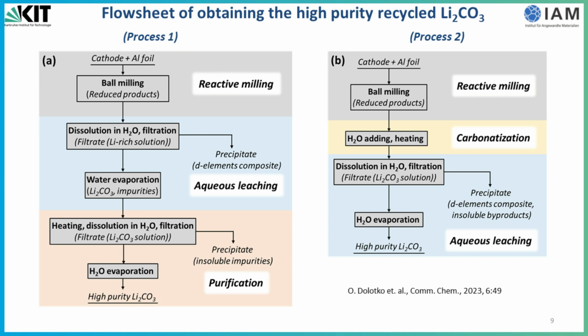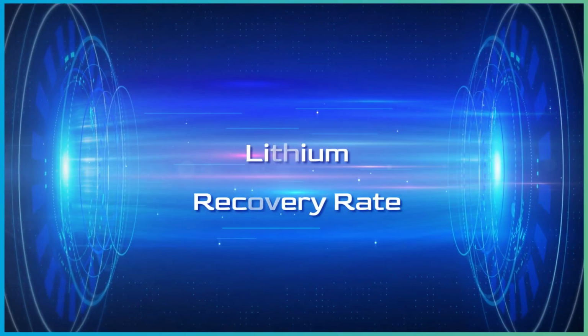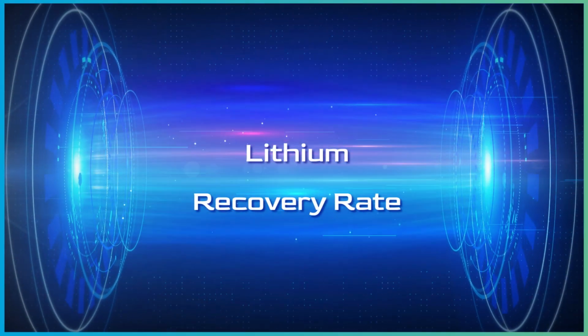In order to reduce the number of steps, we also developed a second process, where after reactive milling, we introduce a so-called carbonatization step. After this step, after washing, leaching with water and filtration, we obtain again high purity lithium carbonate salt. If we analyze the lithium yield of the developed processes, we can clearly see that we have a significant increase in the amount of recycled lithium in the process too.